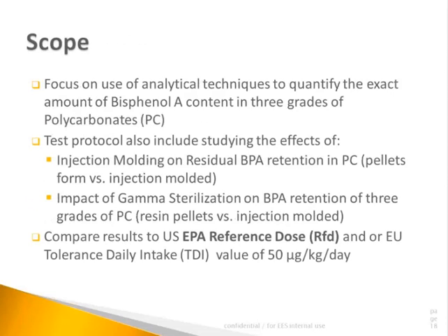The scope of the research is the utilization of analytical technique to quantify the exact amount of bisphenol A in 3 sources of polycarbonate. The test protocol included the investigation of secondary operations such as injection molding and gamma sterilization techniques. Gamma was selected because it is widely used in the medical industry as the most preferred sterilization method due to its cycle time and cost benefits. Results were then compared to the US EPA reference dose, which is the same as the EU tolerable daily intake of 50 micrograms per kilogram per day.